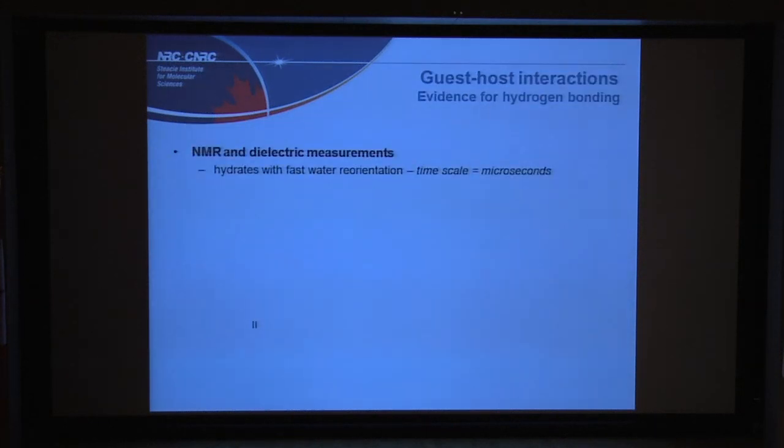So to look for these guest-host interactions, which must exist in these oxygen-containing molecules, the old measurements where this became apparent showed that the hydrates had fast water reorientation times, and this was measured on a time scale of microseconds.